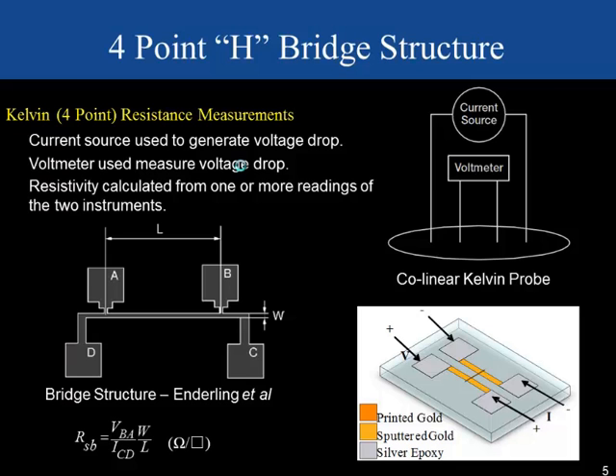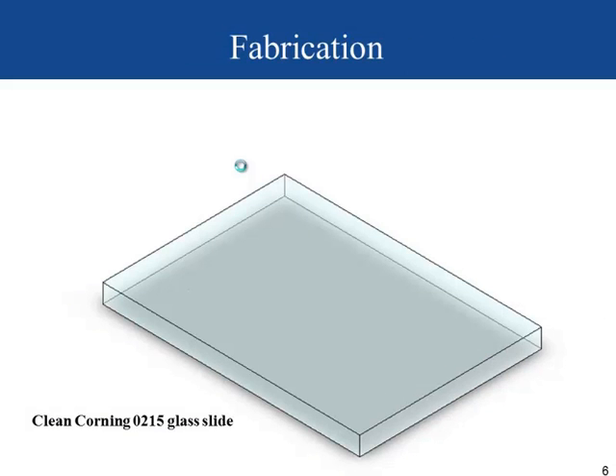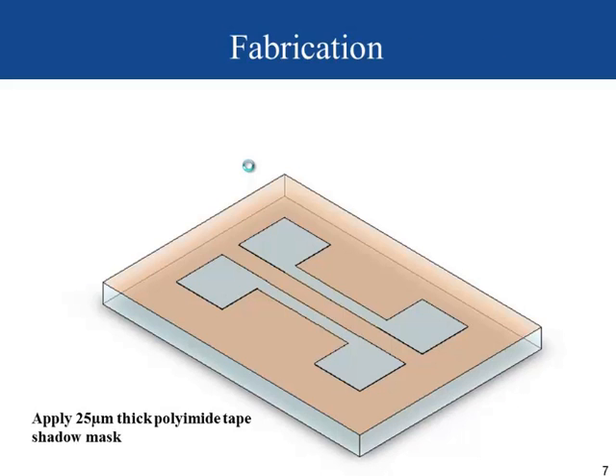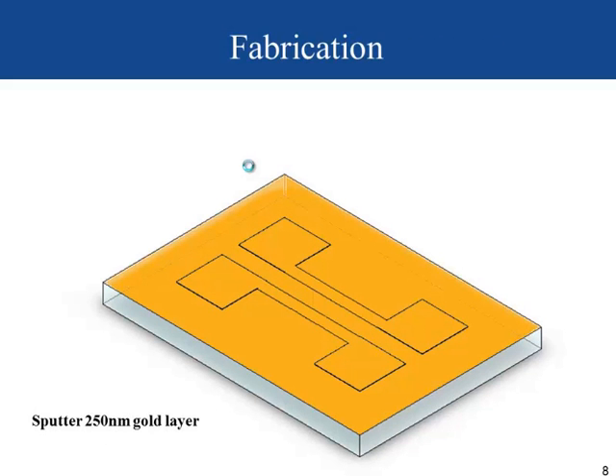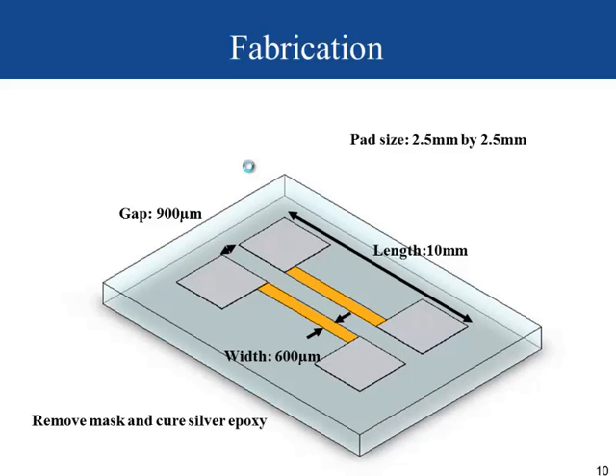For our work, then, we wanted to extend this to allow the use of this kind of structure for the measurement of inkjet printed films. And so we've developed a test structure, which I'll detail the fabrication of in a moment, to use this form of measurement for our work. To do this, we start with any substrate, in this case a clean Corning 0215 soda lime glass slide. We then use a polyimide shadow mask that's laser cut to define the shape of our pads with a gap. A 250 nanometer gold layer is then sputtered onto the surface, and this is kept thin in order to minimize the effects of stepping across with our inkjet printed films. Silver epoxy is then applied to the pads to enhance probing robustness, and then the shadow mask is removed, and the epoxy is allowed to cure.